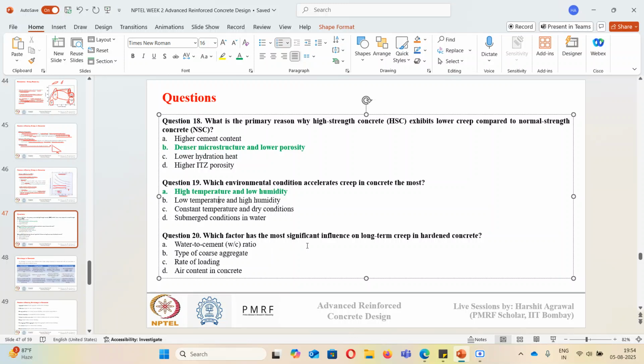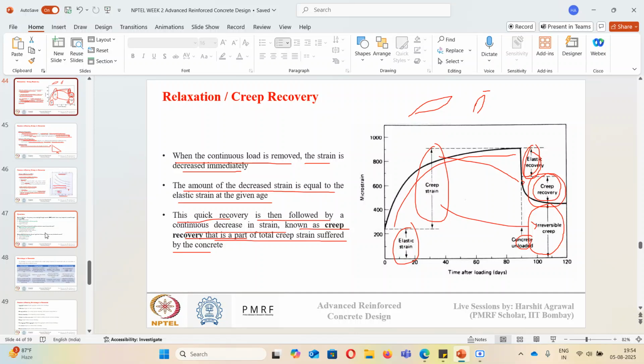Which factor has the most significant influence on long-term creep behavior in concrete? So the correct answer will be A again. So the higher the W by C ratio, the more the porosity, and then the higher will be the risk of creep effect due to moisture movement and weak cement paste structure that is there inside the concrete. So we have all understood that from these points that we discussed. Okay. Any doubts in these questions?